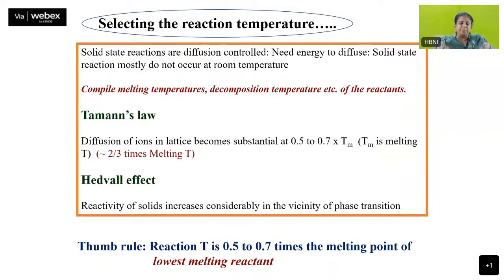Selecting the reaction temperature. So we know that as a diffusion control and the movement of the ions need high temperature. So what we do is, let's say I have reactant A and reactant B. Now there is something called Tammann's law. Tammann's law states that for any material, the diffusion of the ions, I want two reactants to diffuse towards each other, so I want them to be mobile. So Tammann's law states that for any material, the diffusion of the ions becomes substantial at 50 to 70% of its melting point. It's a very rough range.